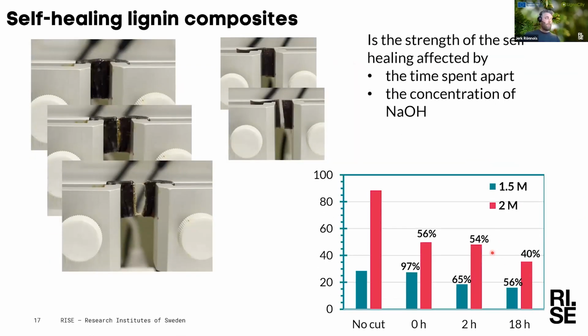And we also tried out if the strength of this was affected by the time spent apart. So if we pull apart the material and let it wait for a while before putting it back together, will the healing be better or worse or similar? So we can see for these bars, these are 2 modes of preparation. We can look at only the pink bars. So before cut, we have this strength. After cutting it and putting it right back together, the strength of it is reduced to about half.